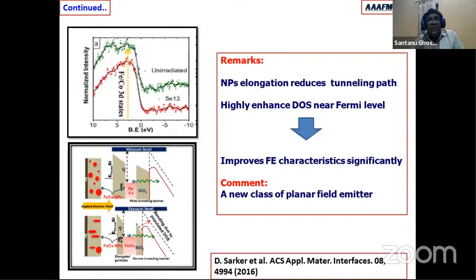Another is, in ultraviolet photoelectron spectroscopy, what we have observed is that there is an enhancement of density of states of electrons near the Fermi level, which actually makes this electron tunneling much easier, eventually leading to the higher current density. So it is basically a combination of two effects. One is elongation of the particle, making an easy path of electron emission. Another is enhancement of the density of states near the Fermi level, and combining these two gives very high current density of the shape engineered particle.